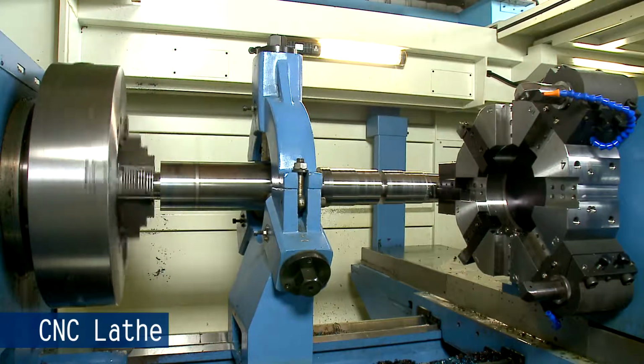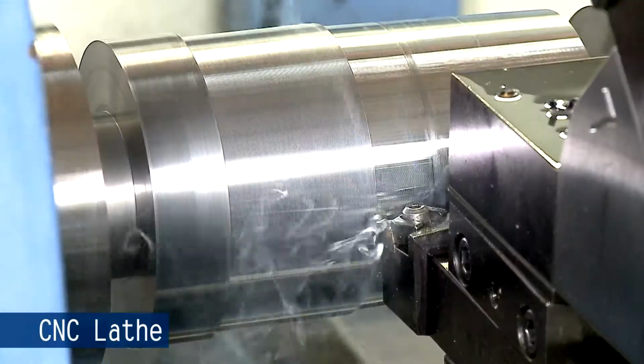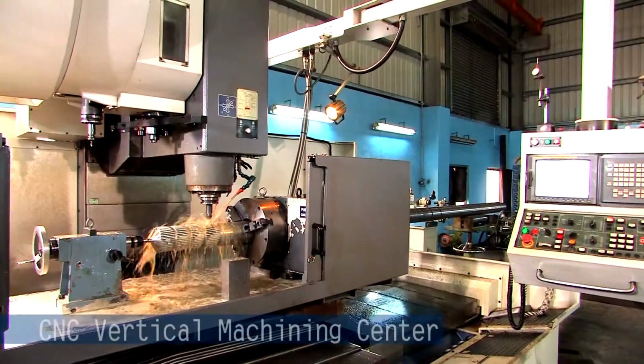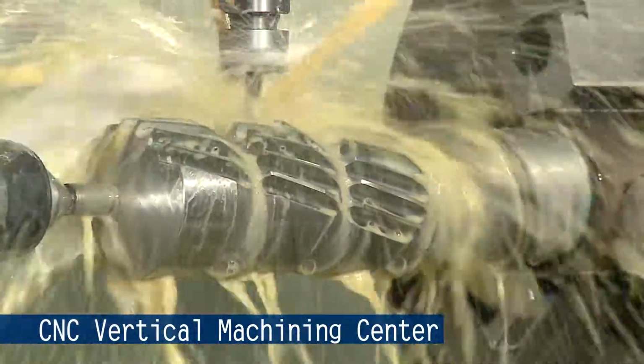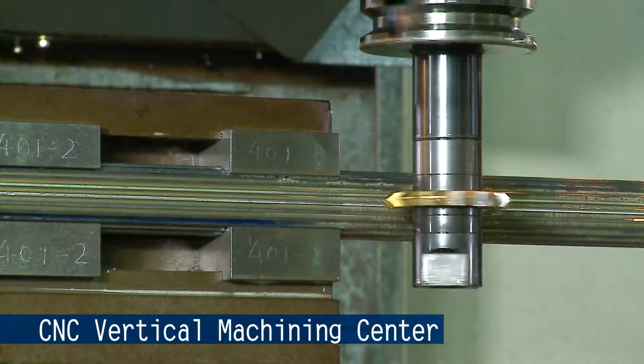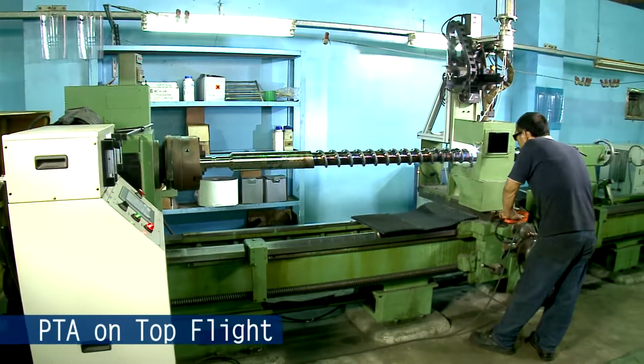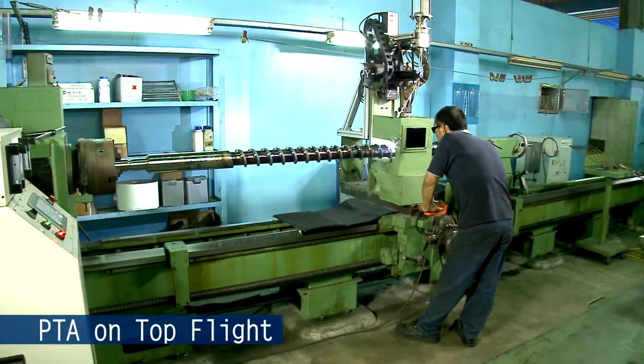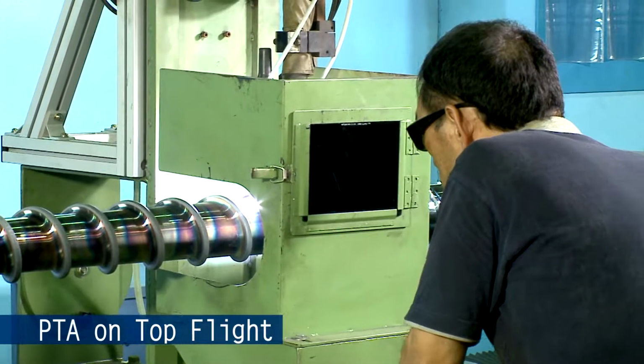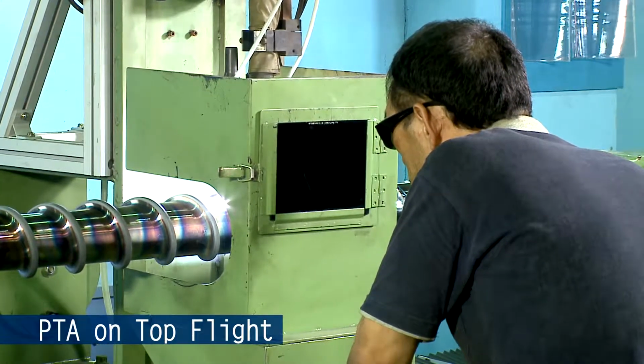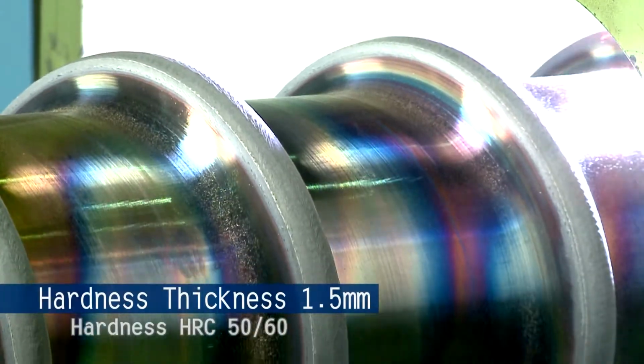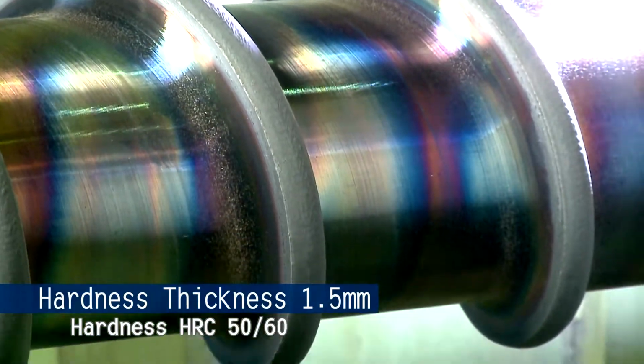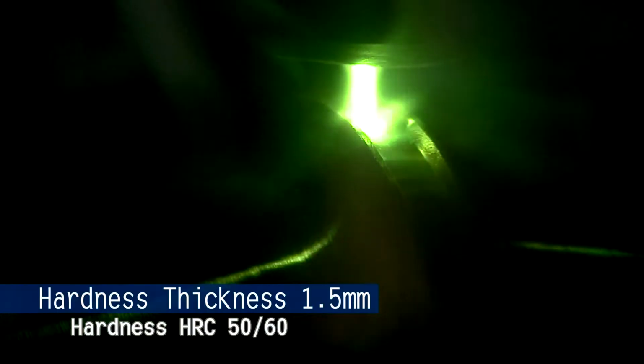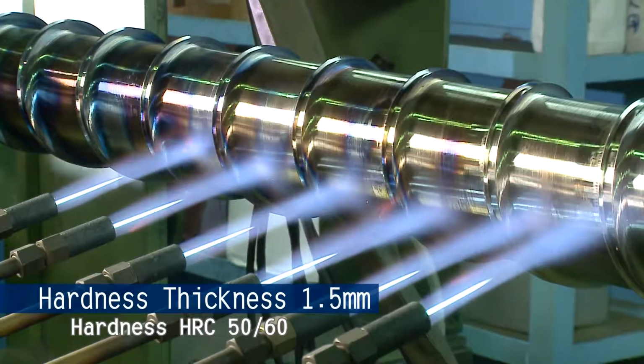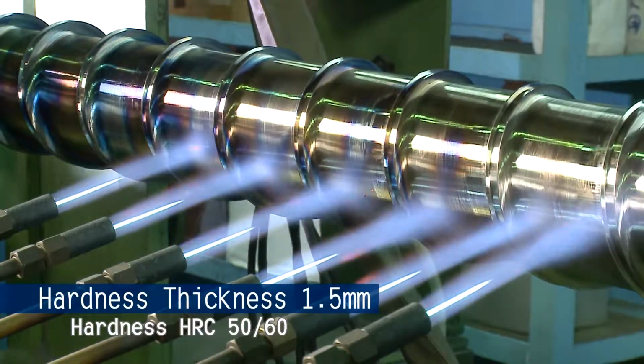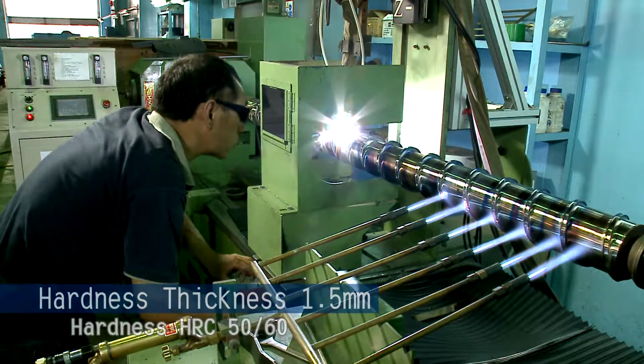For a screw to perform its main functions, such as material feeding, conveying, compressing, melting, exhaustion, and homogenizing on the machine, the PTA nickel tungsten-based alloy spray welding technology fuses the weld tracks and the base metal completely. The hardness layer of a single side is 1.5 millimeters, with a hardness of HRC 50/60. It is durable against wear and corrosion, greatly extending the service life of the screw.